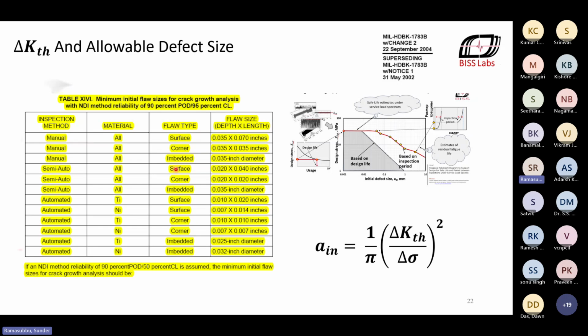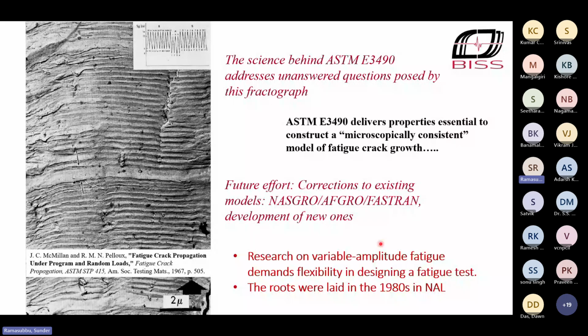Over here, this is a table which I pulled out of the MIL handbook for engines. For aero engines, the allowable defects are in the range of 0.3 to 0.7 millimeters. Now, if you look at the size of a defect as a function of ΔK threshold and the applied stress amplitude, you will see that the defect size is a function of the square of ΔK threshold. What that means is the way you determine ΔK threshold is going to impact this value in a parabolic fashion. That is enough to underscore the importance of getting real material properties rather than properties which are obtained by a method which affects the result. But let me come to something more exciting to me as a researcher.